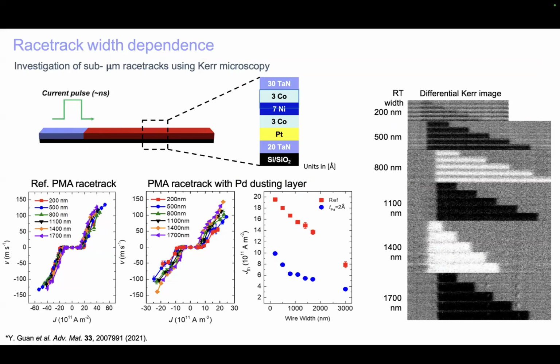So on the right-hand side, if you look at the bottom, you can see a racetrack which is 1700 nanometers wide. Using Kerr microscopy, this technique of measuring the change in polarization of the light, we detect a single domain wall as we apply single current pulses to move it along the racetrack. We take a picture. You can see the black region and gray, that's the domain wall.